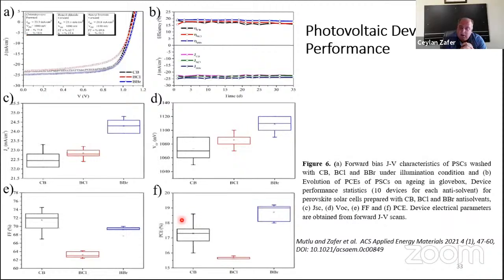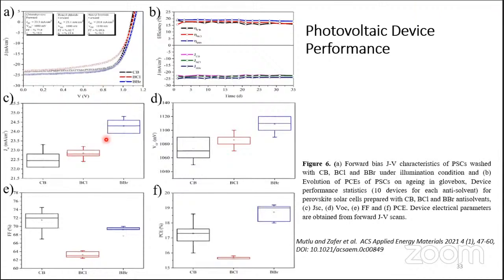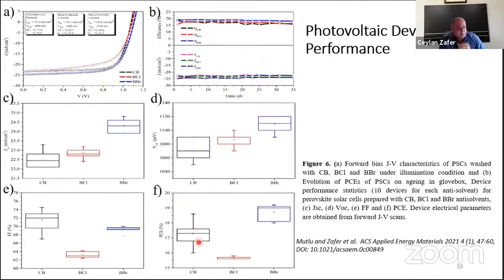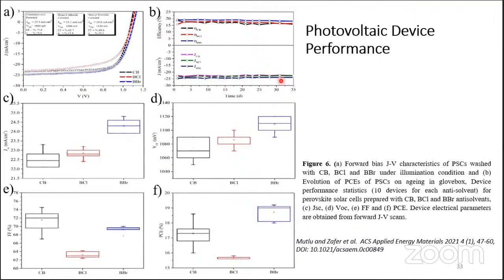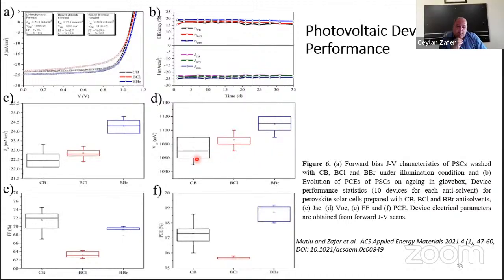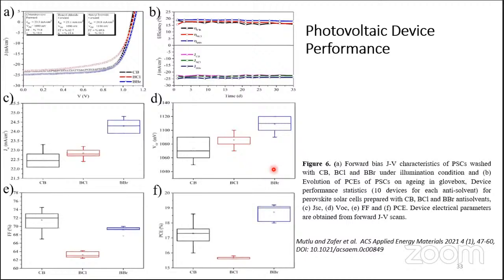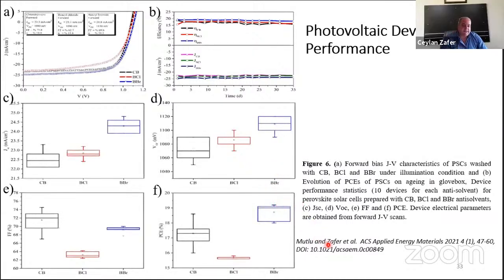What's the result on the photovoltaic performance? Here you see the device efficiency, the black one is the chlorobenzene. These are forward scans with 18.6% efficiency, and with the benzyl bromide 19.2. These are forward sweeps. The reverse sweeps make a big difference compared to the benzyl perovskites, when you make a forward scan, because there is a small hysteresis between the forward and backward scan in perovskite solar cells.